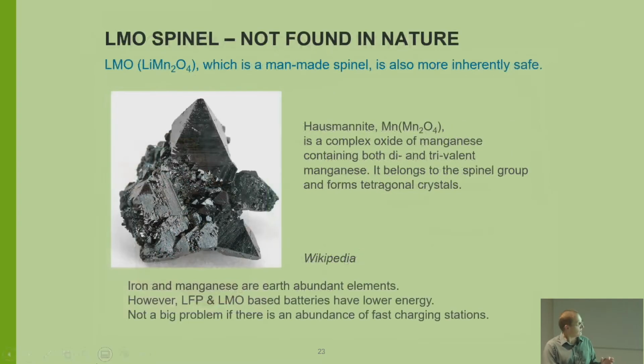Next is the spinel, lithium manganese oxide spinel, not found in nature, man-made, but it's based on the spinel structure. Here's what's called hausmannite. This is that classic spinel structure, 3 cations, 4 oxygens. And if you replace that manganese and put a lithium there, that's how you have that cathode material. Unfortunately, though, with the manganese spinel, when you get to higher temperatures, there are a lot of manganese spinel batteries, but if they get up above 40 degrees Celsius, up over 110 Fahrenheit, you'll start to have what we call manganese dissolution. So when that manganese goes over, it deposits on the negative electrode, and then it just catalyzes more electrolyte decomposition. So generally, you try to keep these batteries cooler. Room temperature is fine. Keep under 80 or 90 Fahrenheit.